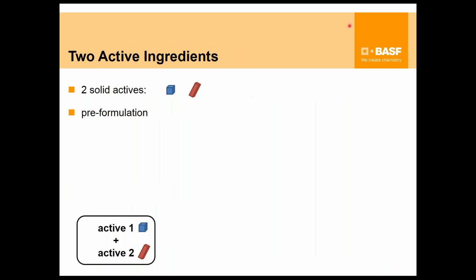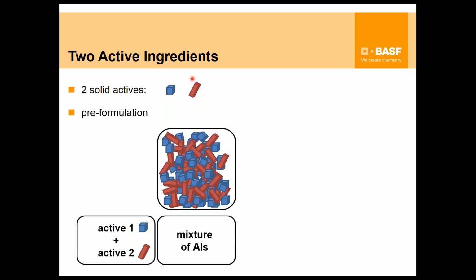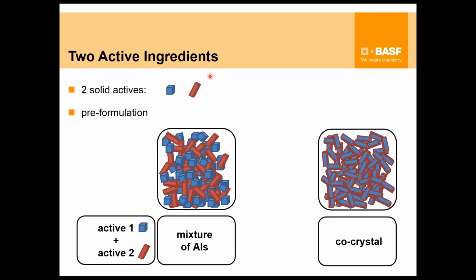I have 2 solid state actives, and I just mark them now as the blue cube and the red prism. And what can happen when I only look at these 2 solid actives? I can have a mixture of my 2 actives, but I also can have co-crystals of my 2 actives. Here I have a mixture of 2 crystalline forms, and they more or less don't interact too much with each other. In this case, these 2 active ingredients form a new crystalline form, and they actually form a co-crystal. So in one crystal structure, both actives are included. I have completely new solid state properties. Actually, I can use this type of co-crystal to make new formulations because I have new properties.